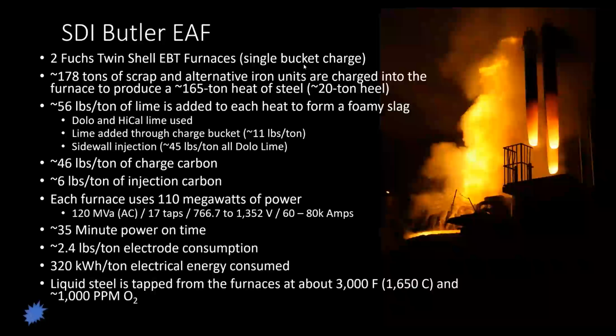That's the idea behind single bucket charging—some electric steel shops, as they're melting, have to stop, pull the electrodes out, open the roof, basically break the arc, add another scrap bucket, and then come back in and start arcing again. There are a lot of papers showing the efficiencies that come with single bucket charging, a significant kilowatt hours per ton reduction. When you open that furnace roof, you lose a significant amount of energy. It's just a big benefit overall.